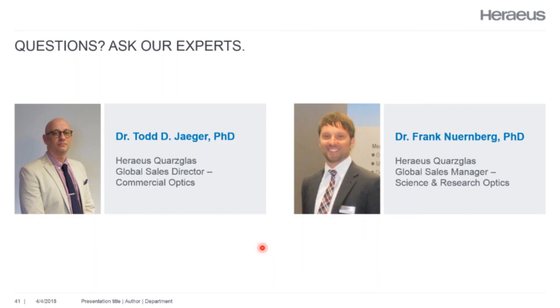So good afternoon, my name is Frank Nürnberg, and I would like to answer all your questions. Regarding the maximum pressure of mostly common application here, pressure windows, it depends on several parameters. It's of course the surface quality, the mounting, and the combination of pressure and thickness. There is a theoretical equation which allows you to calculate a maximum pressure for a certain thickness or vice versa, having a thickness to calculate the pressure. This is a theoretical equation, and this is not containing the lab conditions, and it's very difficult for a material supplier to have more knowledge on the lab conditions. Therefore, certain safety factors are included, but it is really needed to have a live test on site. It can be calculated theoretically, but we would recommend to do really a live test here.